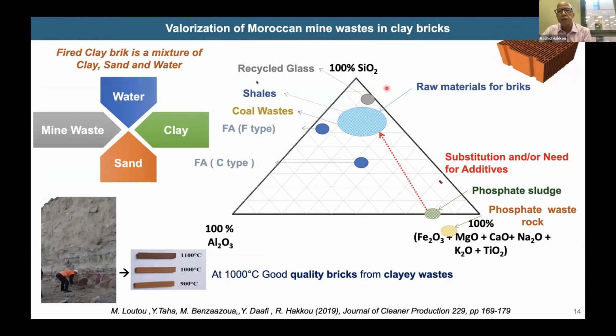It's a mixture of clay, sand, and water. The use of additives has an objective depending on the final product to adjust. So we need alumina to adjust plasticity and silica for vitrification and to obtain higher resistance, and some alkaline and alkaline earth oxides are added to decrease the temperature of firing. That means that in this blue area, we see that we can produce bricks from coal waste.